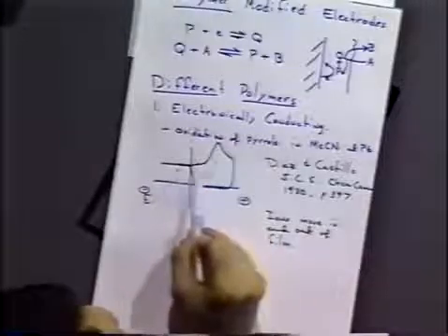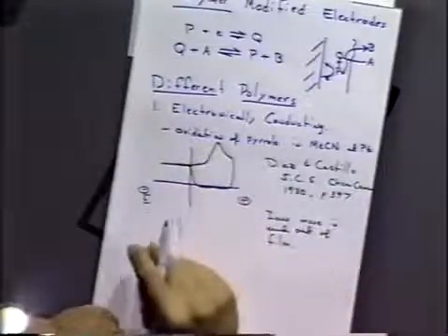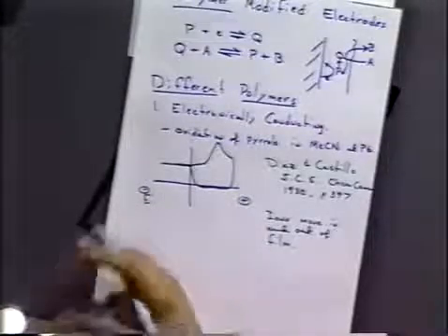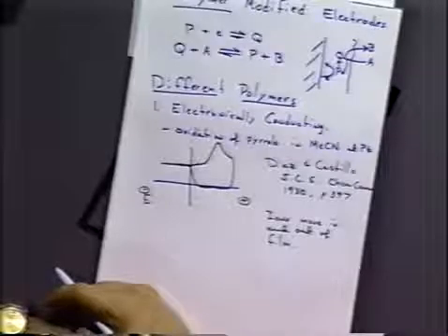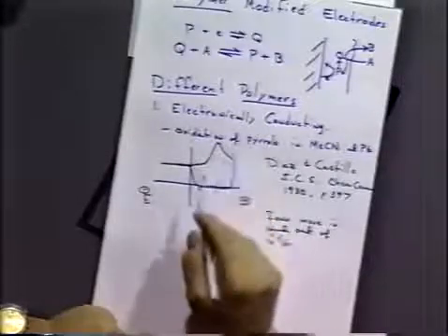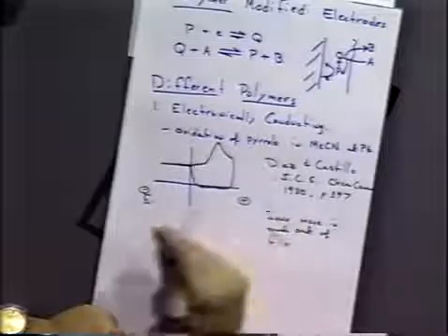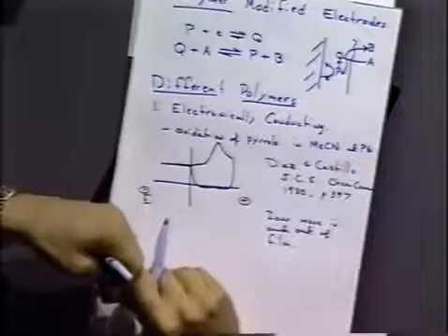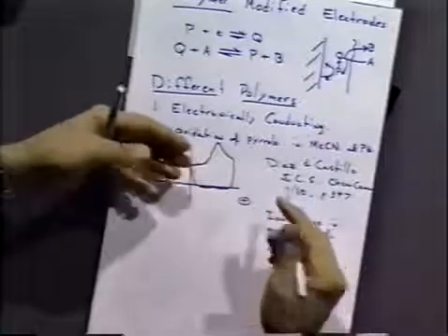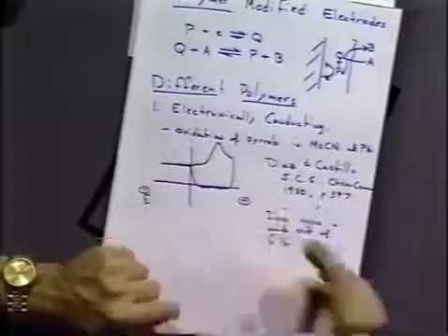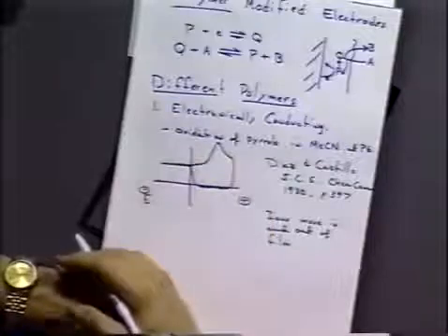Once we've put a positive charge on here, we have to have negative ions coming into that polypyrrole film to allow the reaction to occur. If you don't let negative ions come in, you won't see any oxidation, or very little. And so if you made very large negative ions that just physically can't incorporate into the polymer film, in that case you don't see this sort of behavior. It just doesn't occur. But once you put in smaller negative ions like chloride or something, they'll scoot right in and do the reaction that you need.